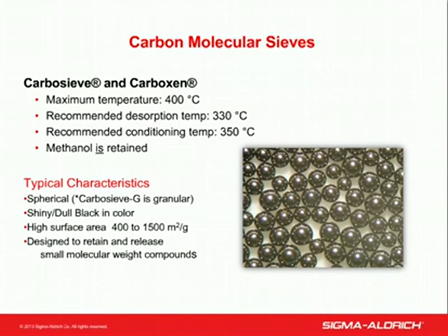In most applications, a weaker bed of a porous polymer or a graphitized carbon black should be placed in front of it to keep the heavier compounds from becoming irreversibly adsorbed. The only time a carbon molecular sieve should be used by itself is if we are confident that our sample doesn't contain compounds with boiling points greater than benzene.